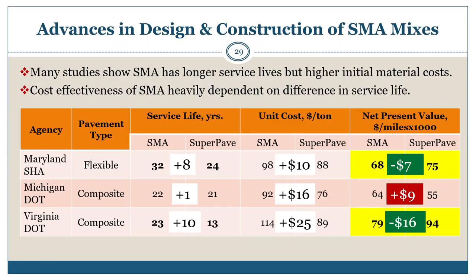The net present value is shown in the columns to the right. There is a $7 per ton reduction in net present value for the SMA mixtures as compared to the Superpave because of the longer service life. So it's cost effective. The Virginia report on the average shows a $16 per ton reduction in net present value for SMA mixtures compared to Superpave, while the Michigan data showed a $9 per ton added net present value for SMA mixes compared to Superpave.